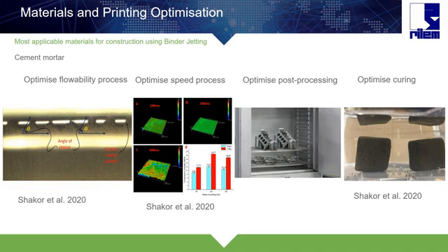Also, it's necessary to optimize the material in a curing liquid. Maybe we need a different type of liquid, but for cement mortar we have been using only water, and the specimens cured in good shape and gave very good results when cured in water. But for some other materials such as geopolymer, we may need a different kind of liquid to get better compressive strength after curing.